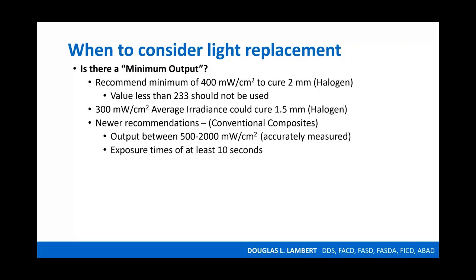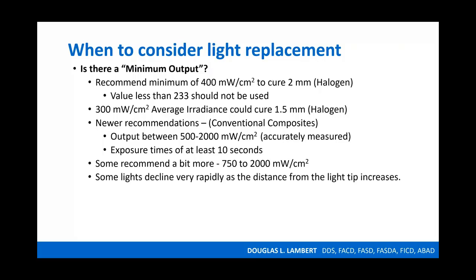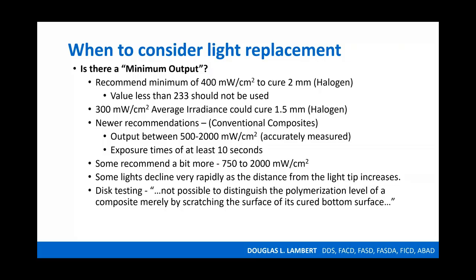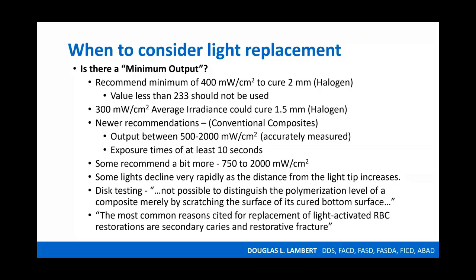I think the newer recommendations we have to look at with the LEDs are, we want a light probably no less than 500 milliwatts per centimeter squared, and really no more than 2,000 milliwatts, and exposure times of at least 10 seconds. You can vary that. I like to say that 1,000 milliwatts is my base to work from. The lights do decline rapidly, some more than others, and you want to make sure you're keeping that accurate data. That's why, again, the checkup system may be important to your practice. Other types of testing, like disc testing, just are not possible to distinguish the proper curing. And the most common reasons cited for replacing composite restorations are the loss of the material itself from fracture and secondary caries. So if we're properly light curing, that's going to absolutely improve our outcomes for our patients.